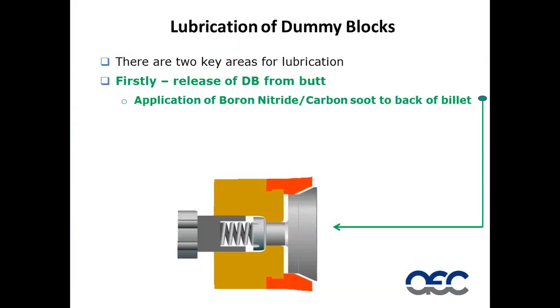Lubrication of dummy blocks, there's basically two key areas. We have the lubricant, or I prefer to call it the release agent, that's put either on the face of the mandrel or the back of the dummy block. And this can be either acetylene soot or boron nitride. And the boron nitride can either be applied as a liquid or as a powder.